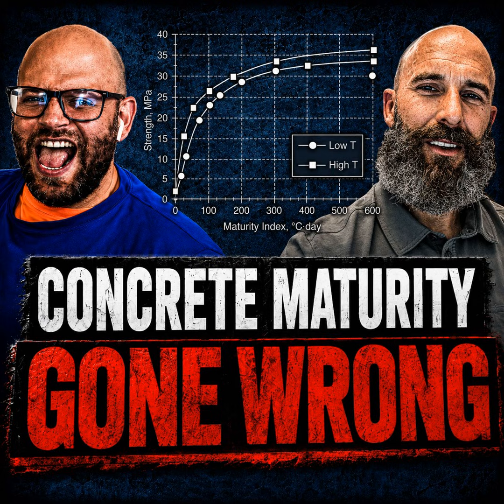Mm-hmm. Right? If I say my datum temperature is really low, that means my cement can take off like a bat out of hell, like the type 3. If I say my datum temperature is really high, that means I have a very coarse grained or slow setting cement, or it needs that temperature to kick off. That makes sense, right? Yeah. So if I tell my maturity logger that the datum temperature is really, really low, it'll change the graph by pushing it up. It'll tell me to strip forms too early.